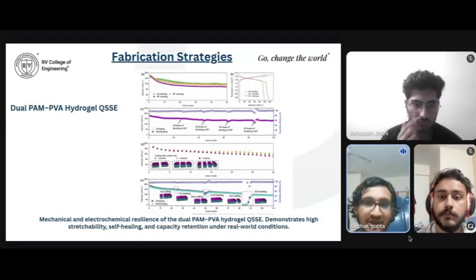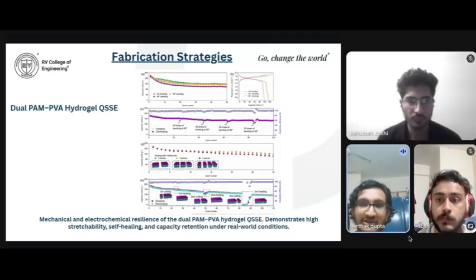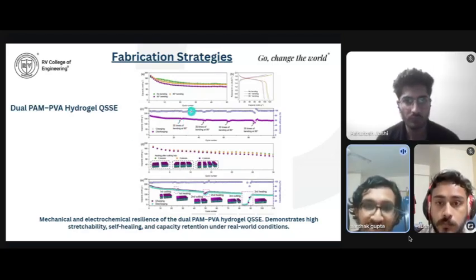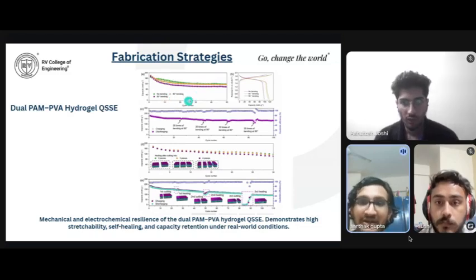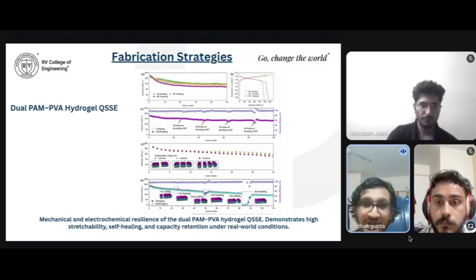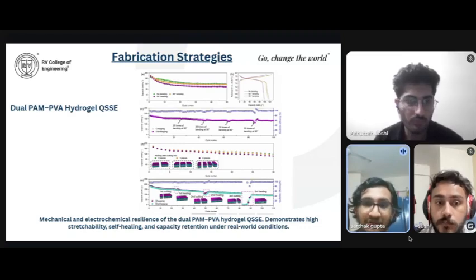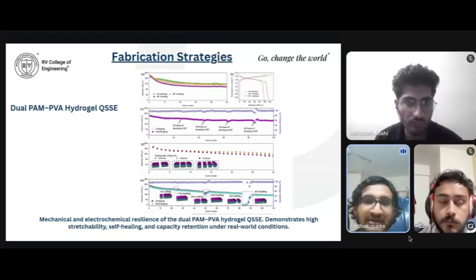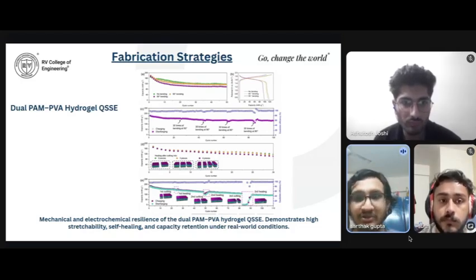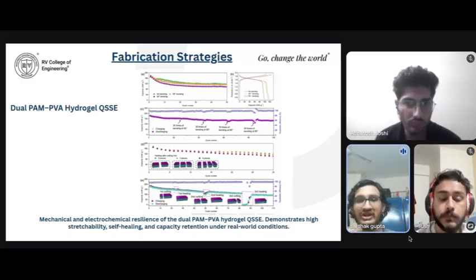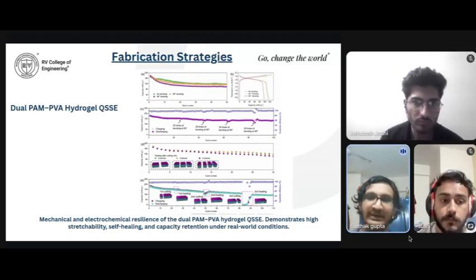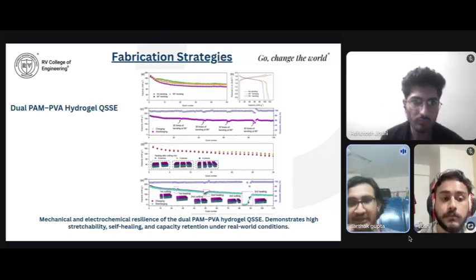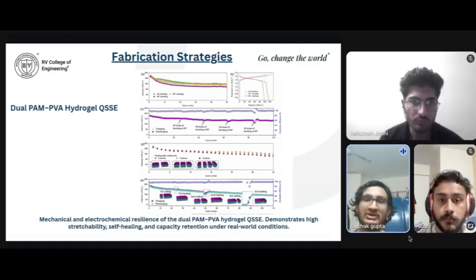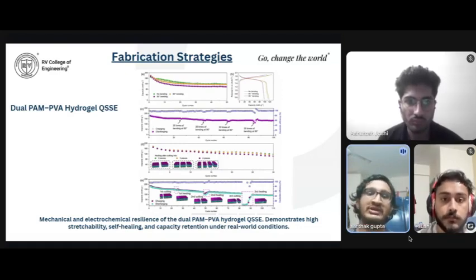This is one comparison of how the electrochemical resilience is coming. In the first case, we can see there is no such effect of bending on the electrolyte. When we come to the bending part, in the second panel we see the GCD, galvanostatic charge-discharge profiles under bending. It shows the charge-discharge voltage profiles under the same bending angles. We can see that even after bending at 90 degrees, the curves do not collapse, indicating that the hydrogel QSSE retains its electrochemical integrity and capacity delivery under mechanical strain also.